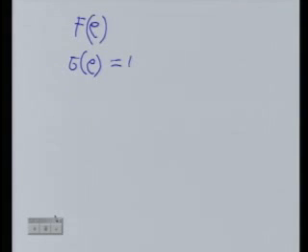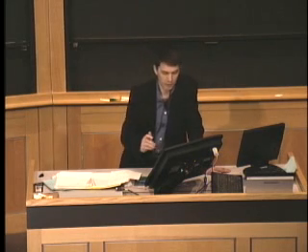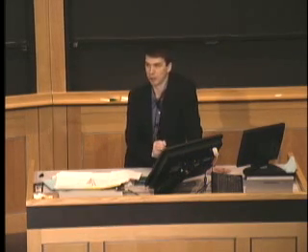The way you can see that the potential is not unique: if I have an embedding function, f of rho, and I define another embedding function, let me call it g of rho, where rho is the electron density, and I say that's f of rho plus some linear term in rho, you can make the total energy function exactly the same with either of the two embedding functions just by changing the pair potential. Let me show you that.